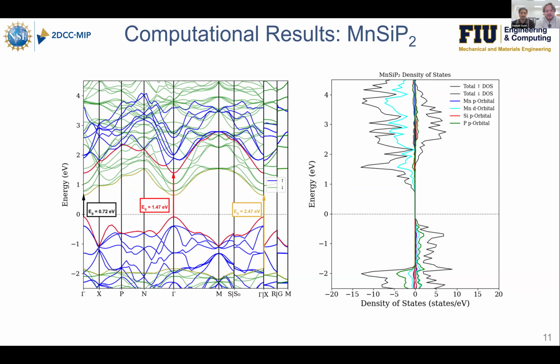And you'll also notice that I've listed three band gaps here. That's because the total band gap, just considering both spin up and spin down, was only 0.72 eV, while the band gap for only the spin up states was shown to be 1.47 eV, which was very close to the experimental band gap of 1.5. And then lastly, the spin down was 2.47.